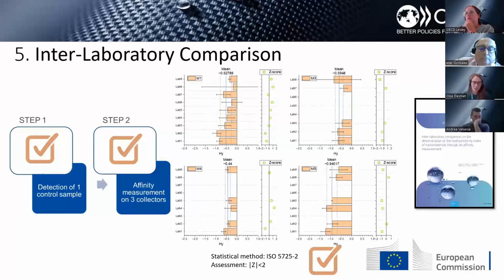I will not spend too much time on the evaluation of the results. You can find all the details in the GRC technical report that was published about it — here is the cover. But in brief, all steps were evaluated using ISO standard statistical analysis, and the final result of the test, the determination of the hydrophobicity index of the different materials, is shown as the main graph on the slide. For this main result, the hydrophobicity index, all results were considered satisfactory, with all data scores being below 2. This permitted us to validate the use of the SOP to measure the hydrophobicity index of the tested materials through the affinity measurement.